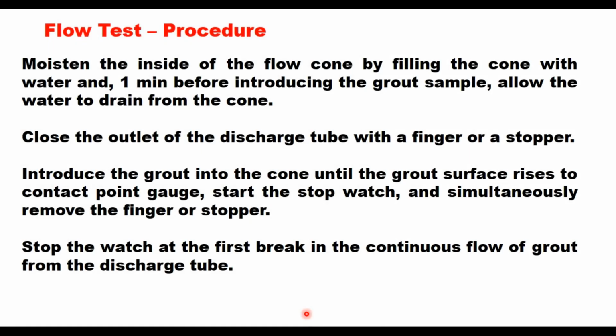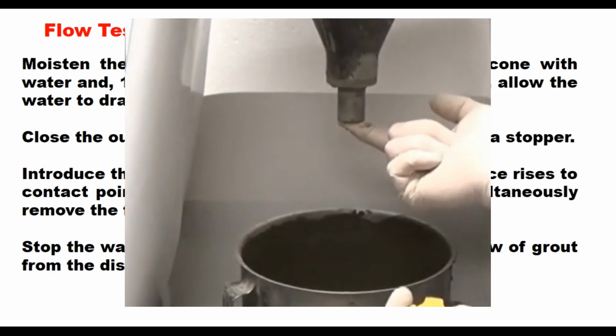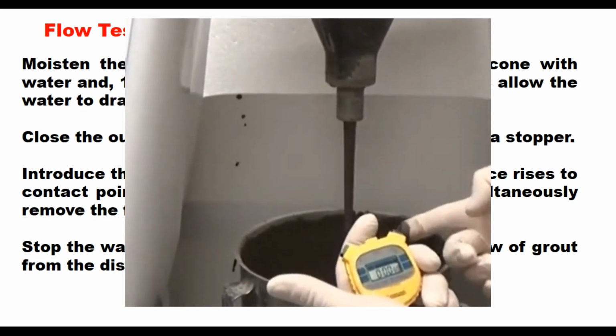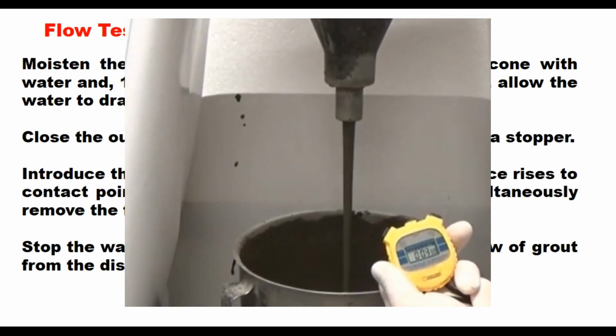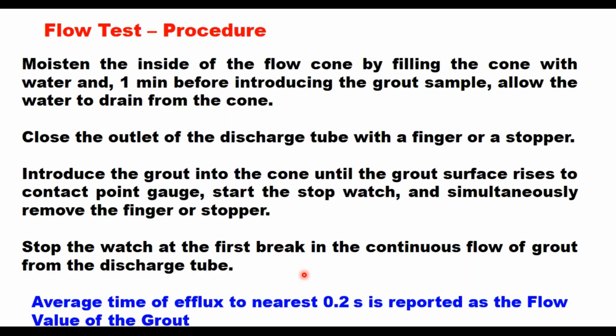The procedure is to moisten the inside of the flow cone by filling the cone with water, and 1 minute before introducing the grout sample, allow the water to drain from the cone. So you fill the cone with water and remove this water just 1 minute before introducing the grout. Then close the outlet of the discharge tube with a finger or a stopper. Then introduce the grout into the cone until the grout surface rises to contact the point gauge. Start the stopwatch and simultaneously remove the finger or stopper. Stop the watch at the first break in the continuous flow of grout from the discharge tube. The average time of efflux to the nearest 0.2 seconds is reported as the flow value of the grout.